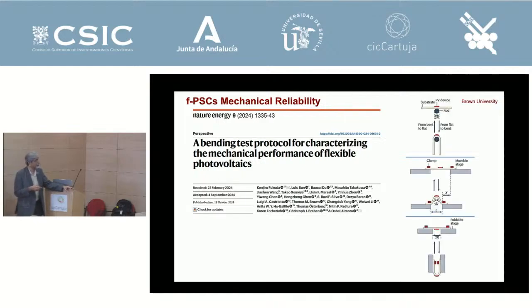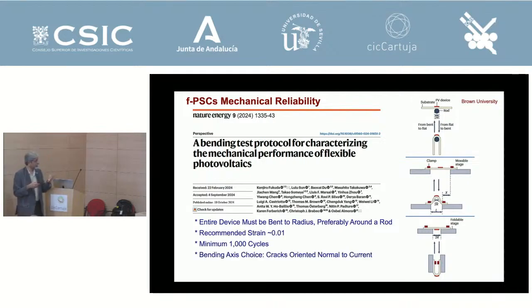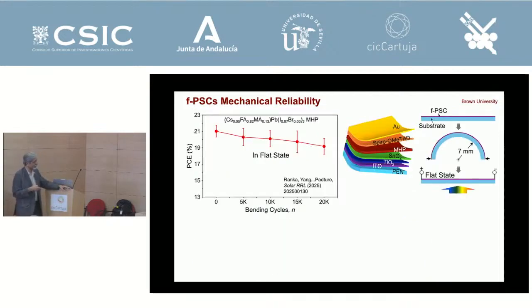And basically we came up with some recommendations, is that you have to bend the solar cell to the entire radius, so everything is in the same stress state. Then the recommended strain, the number of cycles, and the choice of axis is also very important, because a lot of people were bending it in the wrong axis, because if the cracks go this way and the current goes this way, it doesn't affect your current. And so you see very high efficiencies. The current has to go perpendicular to the crack axis, right? And so on, but I won't go there.